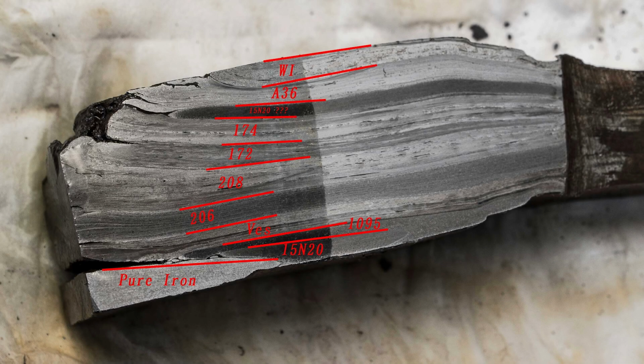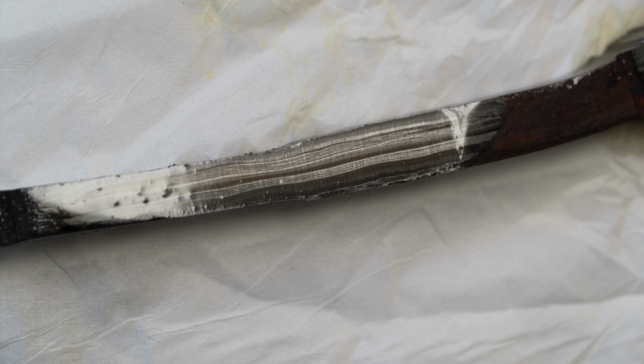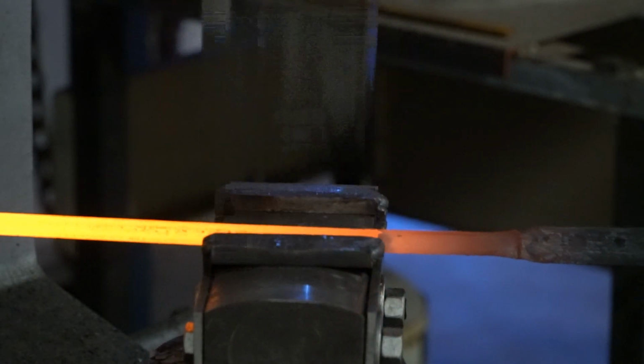This stack has several bars, some of them made with iron, some of them with steel, some of them with phosphoric iron, and I had even added modern steel for comparison purposes. It looks promising. After drawing out and stretching, I can see which bands produce better contrast. This bar will be squared off in order to twist it.